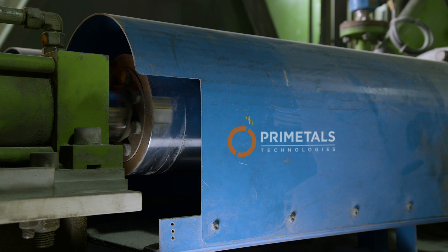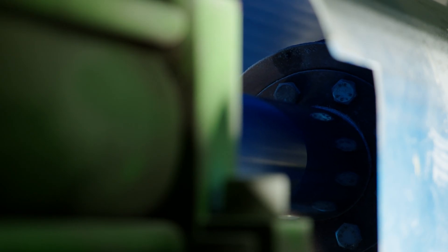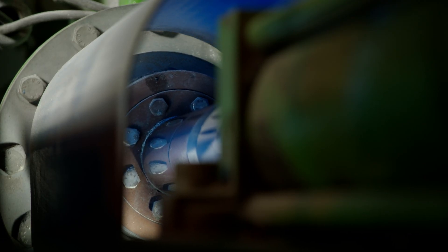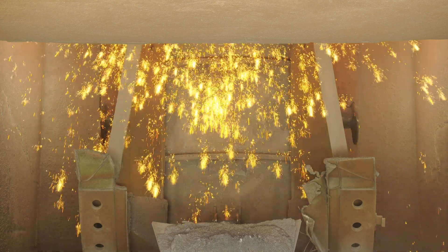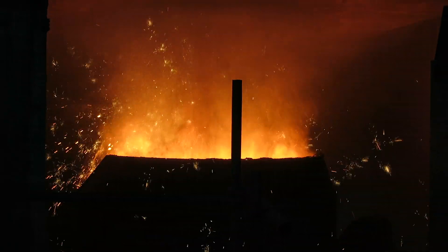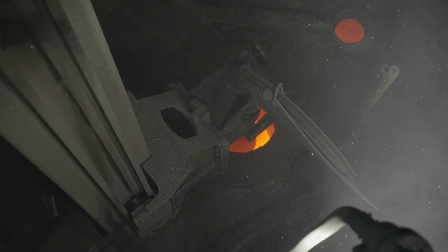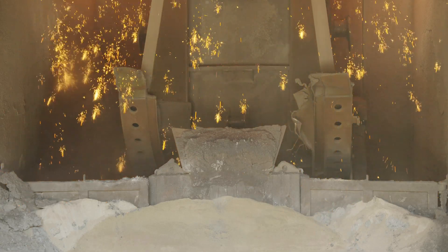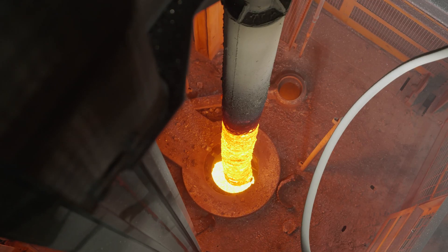The volumetric dosing device has two collateral pistons for the continuous and precise injection of 3 to 15 kilograms per minute of magnesium. Because of the new facility's extremely precise dosing, the consumption of desulphurization agents is now lower than in the previous scenario. Processing times are also significantly shorter.